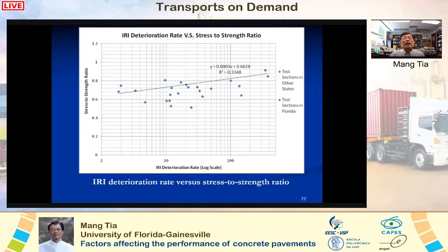When we divided the maximum stress by the flexural strength of the concrete to obtain the stress to strength ratio and plotted stress to strength ratio against IRI deterioration rate, we got a better relationship with a slightly higher R square value. So as the stress to strength ratio increases, the IRI deterioration rate also increases.